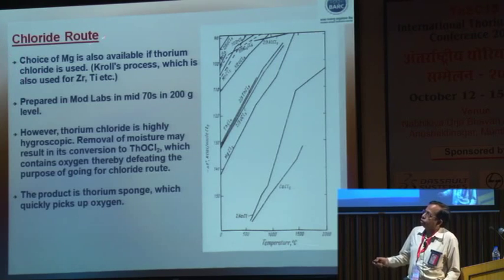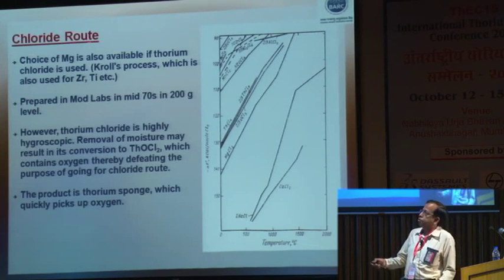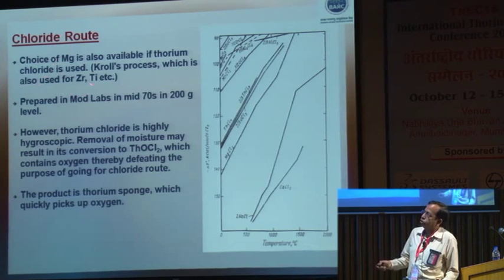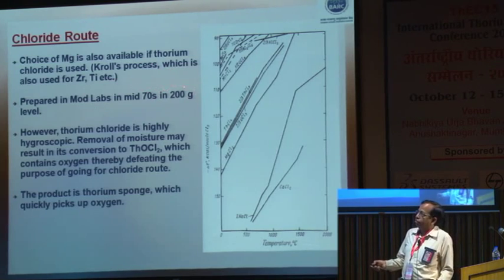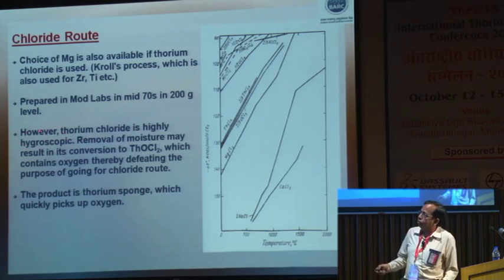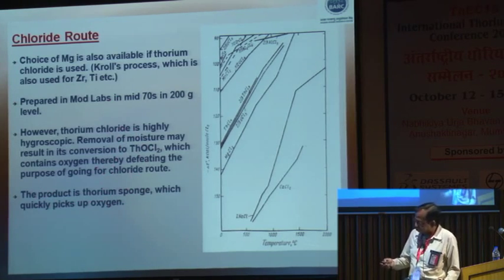The second route is the chloride route, where we use the same process as is done in the case of zirconium or titanium, which is the Kroll process. Take the thorium chloride and reduce it with magnesium or calcium. This process has also been tried quite some time back, and some amount of thorium has been made. However, thorium chloride is highly hygroscopic, and you again end up with the same problem, that is having oxygen in the intermediate stage, and this oxygen will go to the product, and that's not what we want. The other thing is the thorium produced by this method is thorium sponge, which is again very prone to oxidation.